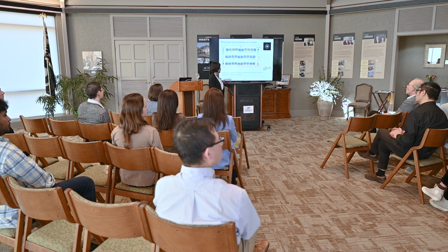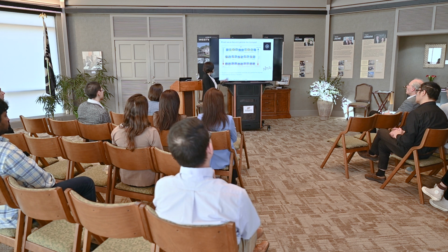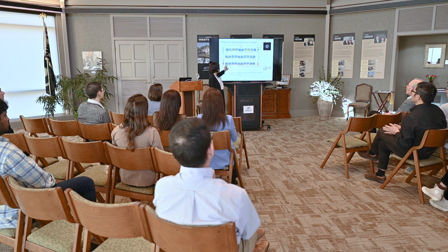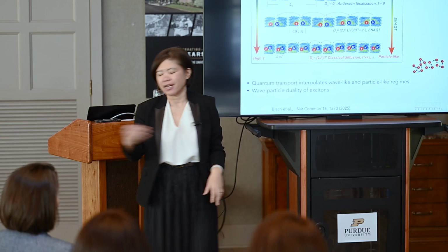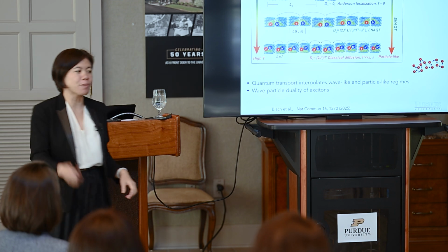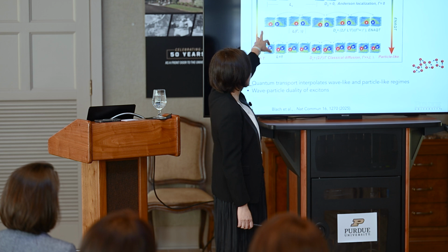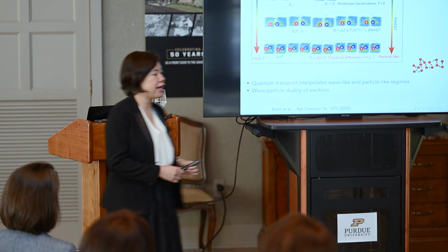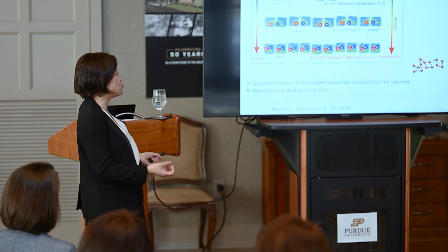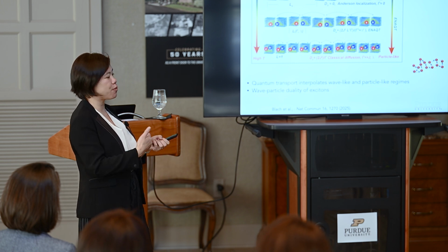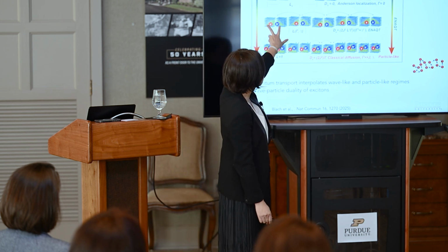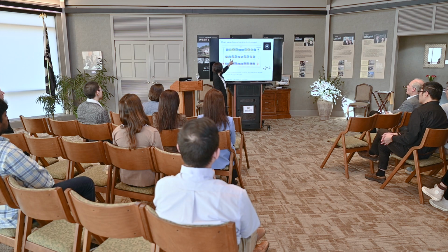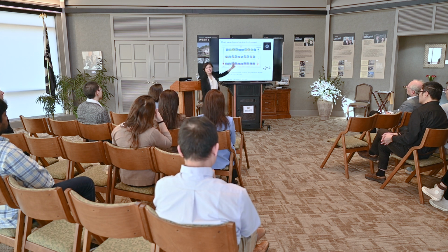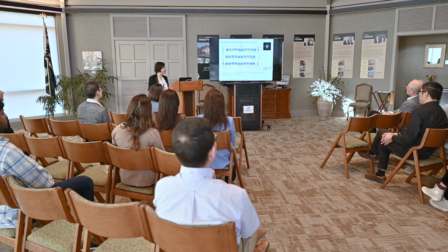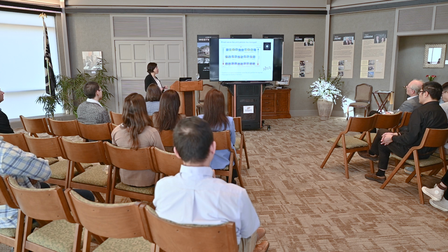At high temperature, because of the fluctuation and the phonons, the wave of exciton is localized to a single particle, so everything is particle-like. The exciton just moves from one to the other, jumping from one to the next. But what's very interesting is that in the middle, there is a maximum regime for its transport, and it has to do with both the wave-like and particle-like transport working together. You still have some wave-like transport, but some particle-like transport allows you to overcome the Anderson localization by jumping to the next one. So this is a case where both the wave and particle-like behaviors are important for the transport.